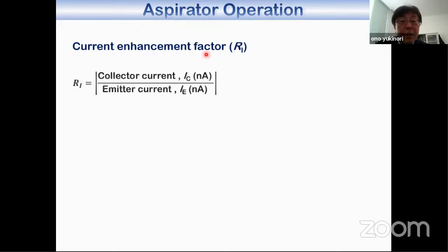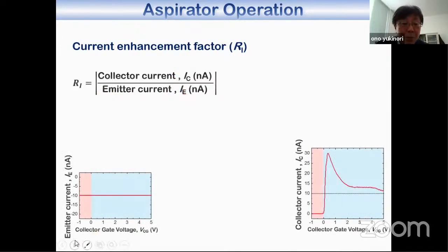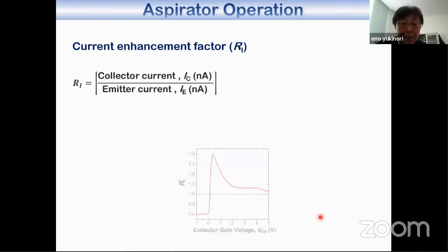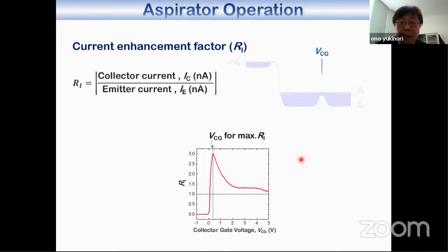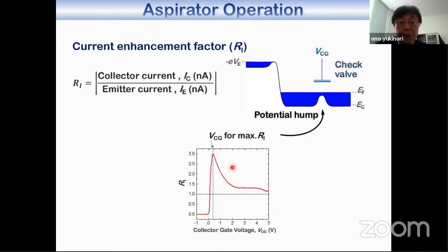So we can define the current enhancement factor, Ri, which is given by the collector current divided by the emitter current. As I explained, the emitter current was kept constant. Therefore, the enhancement factor characteristics are completely the same as the collector current characteristics, like this. And you can see that the current enhancement factor reaches 3 at maximum. I'd like to skip the details of the mechanisms of this peak structure. But at this voltage condition, there is a small hump remaining underneath the collector gate. This small hump prevents the backflow of electrons from the collector to the T-branch region. In other words, the collector gate acts as a check valve of the electron aspirator.